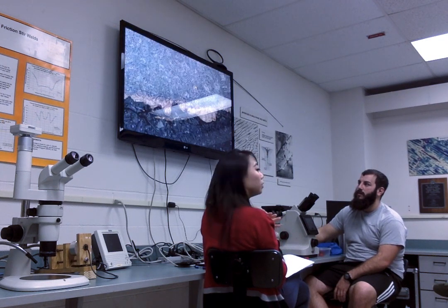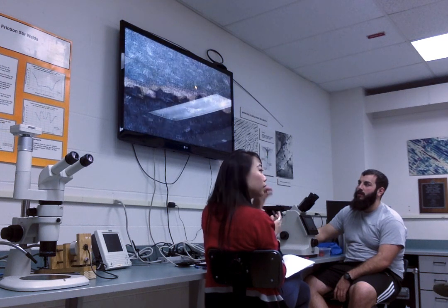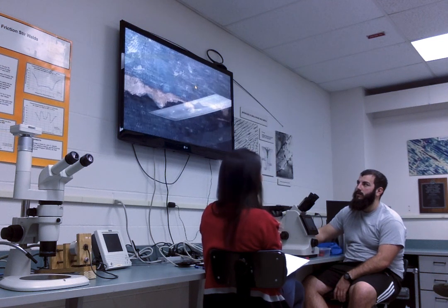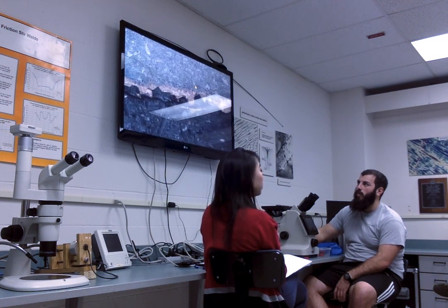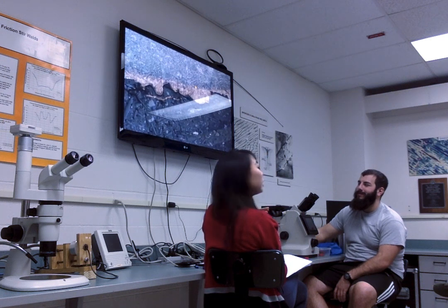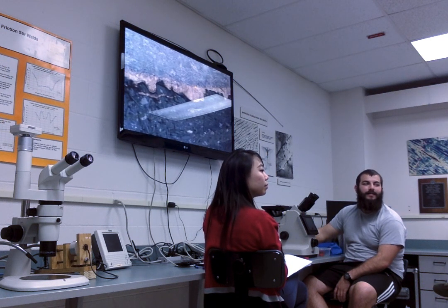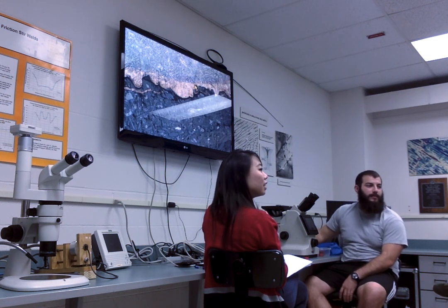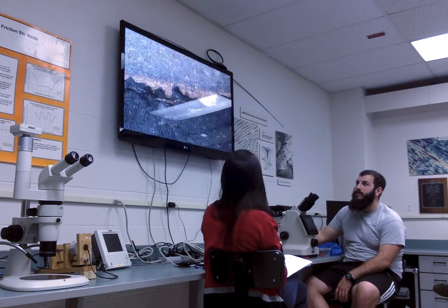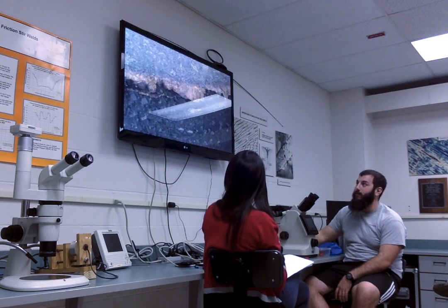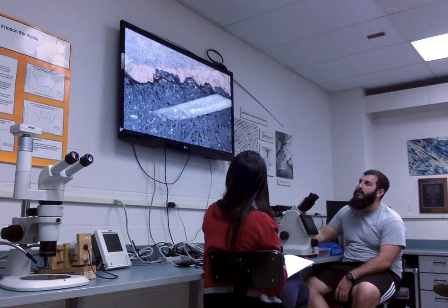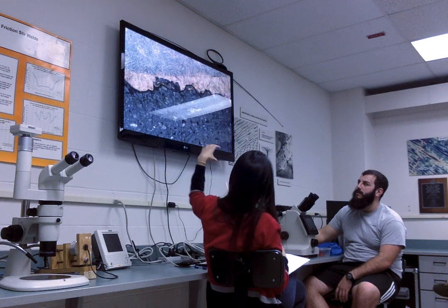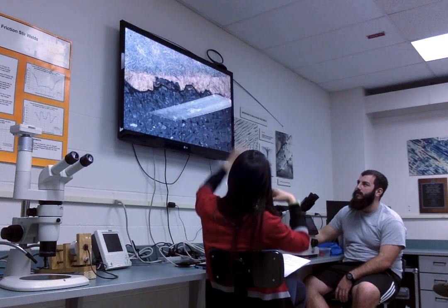So, I see a failure here. What region relative to the weld did this fail? Coarse grain. Right. Okay, good. Do you see any microstructure indicators? Martensite, good. Intergranular or transgranular? Who said transgranular? Where do you see it? If you go to the right, isn't it that step right there where it's really straight? Might be the edge of like three grains.